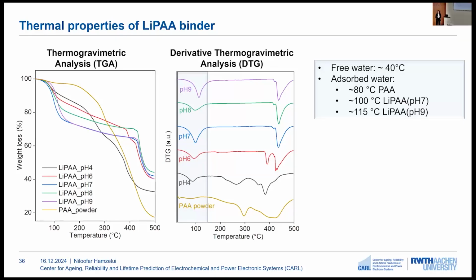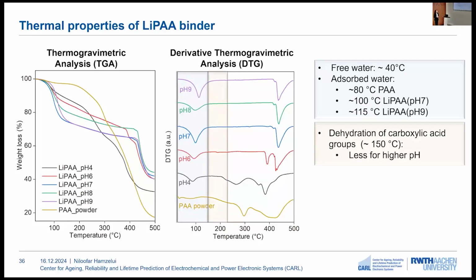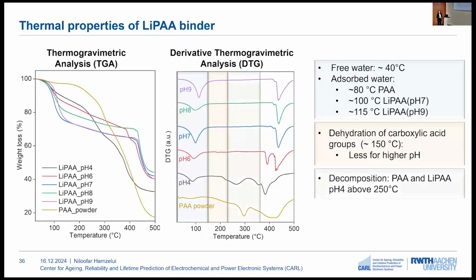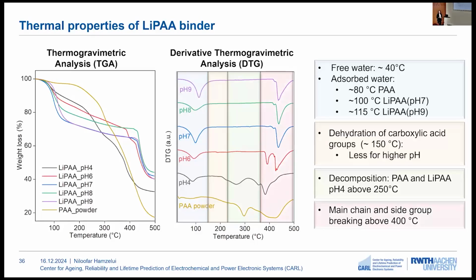So this is an important thing to think about when drying the electrodes which are using the binders with a more basic LiPAA. In the next section, we can see the dehydration of carboxylic acid groups, which happens around 150, and this is less pronounced for the higher pH of the binder. Then in the next section, we can see the decomposition of PAA and LiPAA with pH 4, and in the final stage, we can see the main chain and side group breaking above 400 degrees.